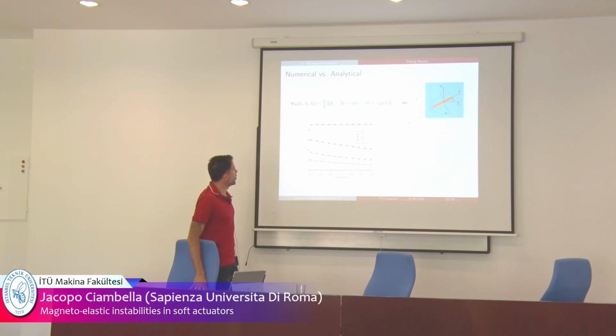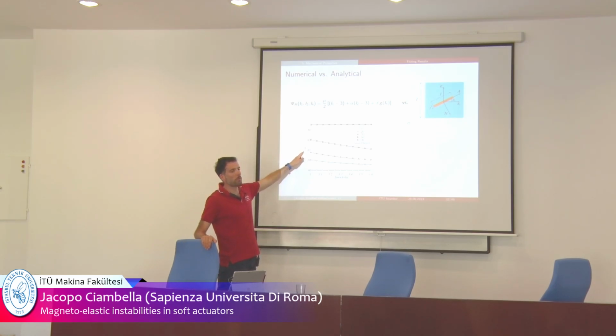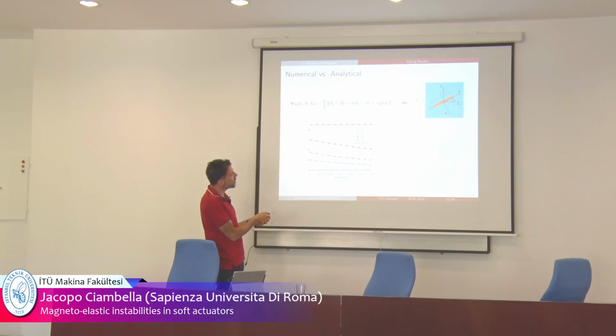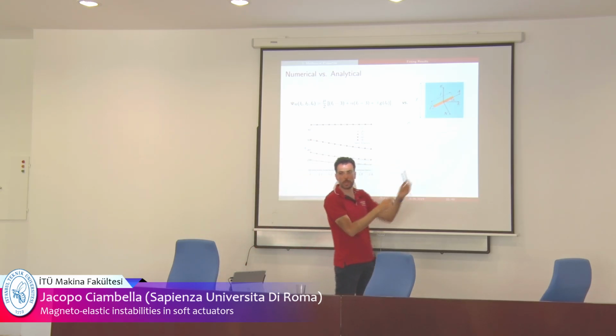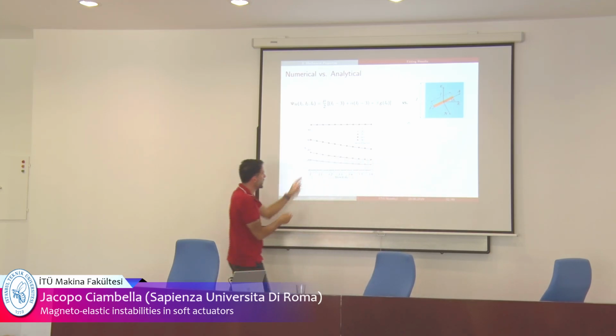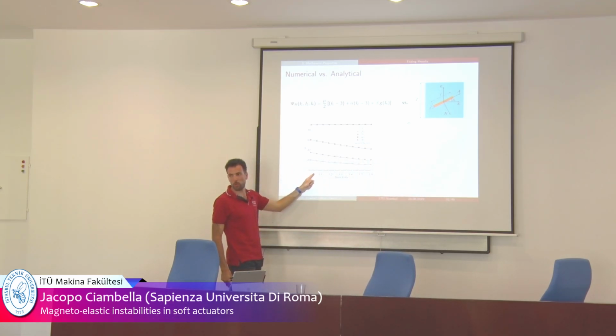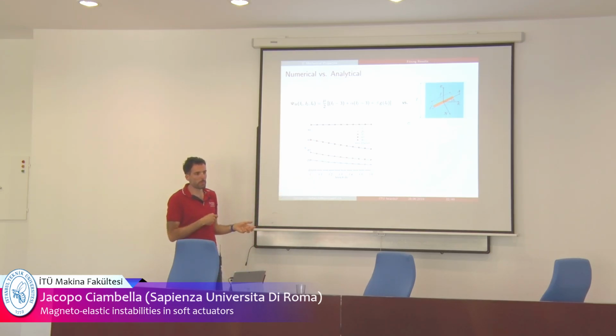And then you can look at how the orientation of the fiber changes with time. Because you are pulling this specimen in this direction, the fibers will tend to orient with the loading direction. So this is the orientation. A fiber which is initially at 90 degrees, perpendicular to the loading direction, won't change its direction. So it will stay at 90 degrees, as expected. The same is true for 0 degree, it's already oriented. The others, of course, will change direction, but the analytical model is quite good at predicting this behavior.